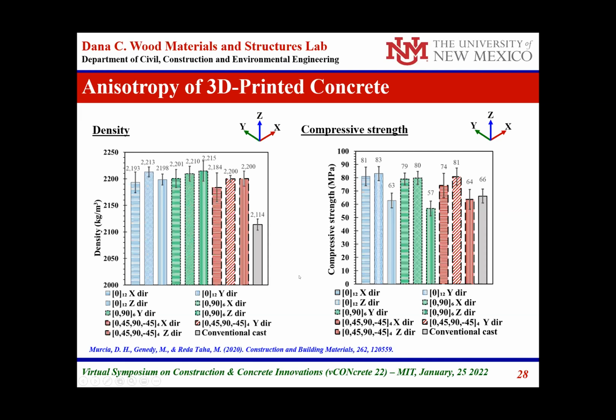We measured the compressive strength of the concrete as well. This is the increase in density. We observed something interesting: the compressive strength in the X and Y direction is actually higher than the compressive strength in the Z direction.